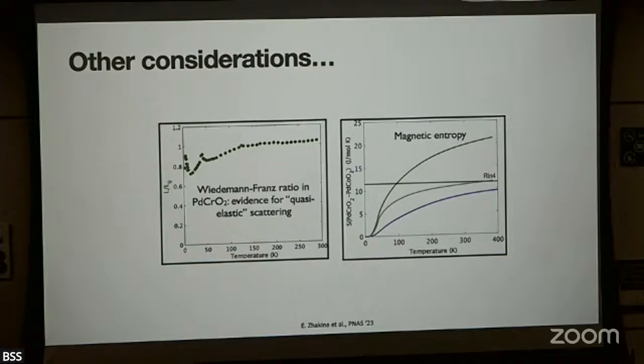Let me not go into this because there's also evidence that in the magnetic compound, the phonons actually soften to some extent. So the coupling to the correlated electronic degrees of freedom leads to a reduction in their effective Debye temperature scale. So why did I talk about this, other than the fact that it's one correlated compound which has local moments where you can come up with a pretty accurate microscopic theory? Because now I want to just raise the following set of questions that you should think about.